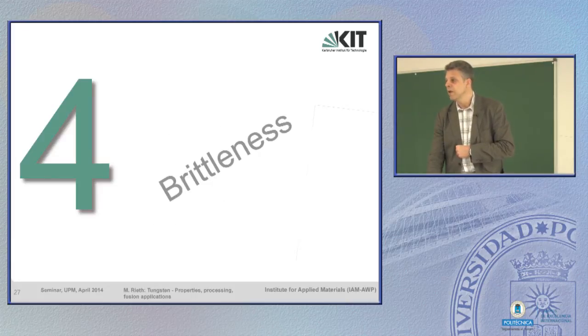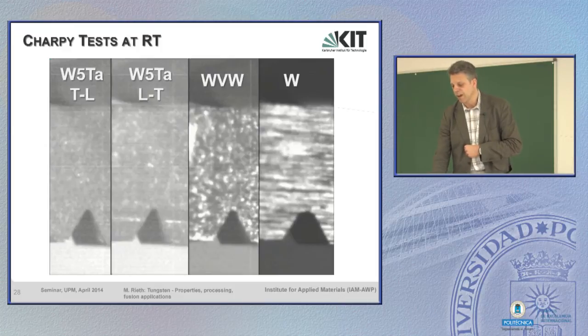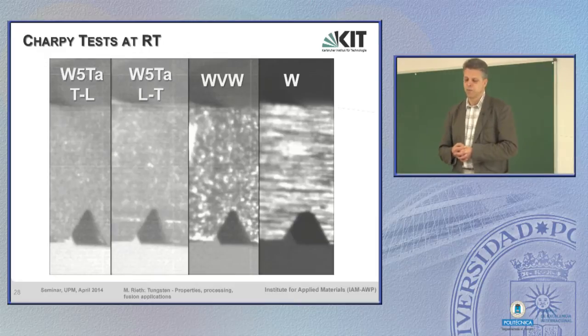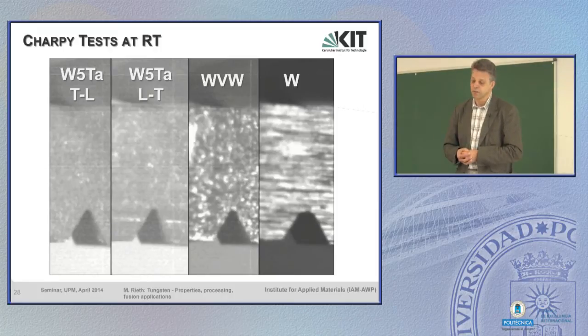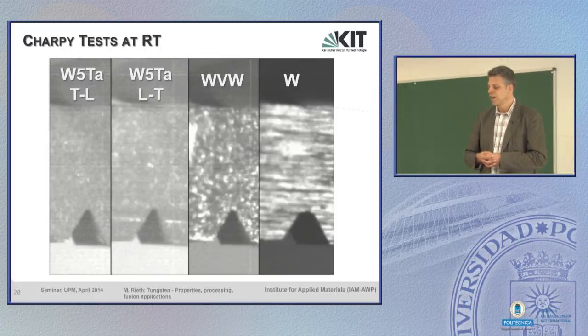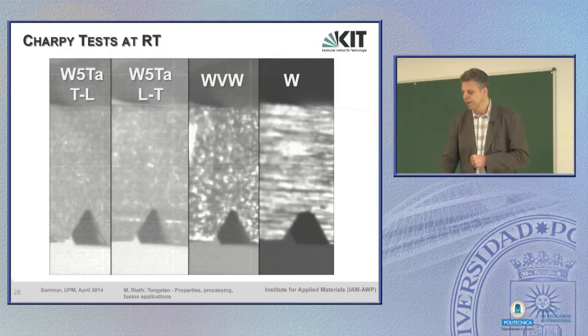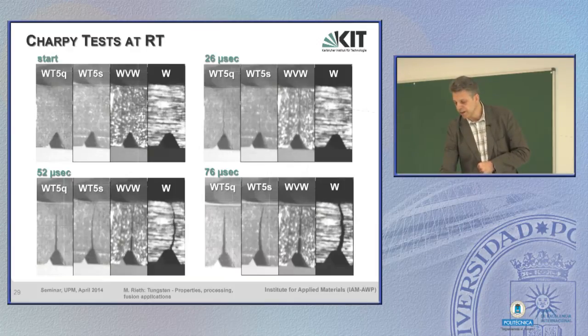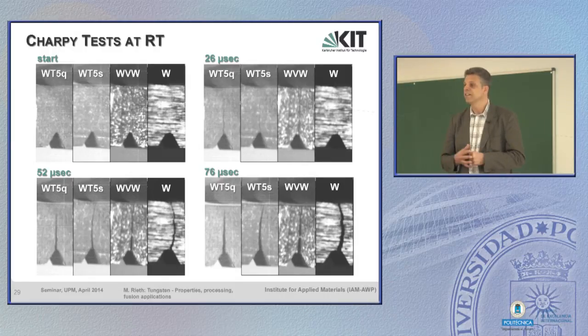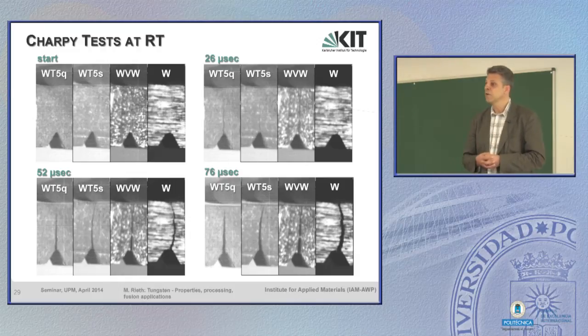Now let's come to the main drawback of tungsten, that's its brittleness. And you see here a Charpy impact during the very first phase of the test, and as soon as the hammer contacts the specimen, here is a variety of tungsten material, you see an immediate fast fracture which goes completely through the material or through the specimen. Here a sequence, this is the start, and right after about 20 microseconds you see already fast fracture evolve, and well, after 50 microseconds or so the cracks have already gone through the 3 mm of the specimen type. So this is a real brittle material. These tests have been performed at room temperature.